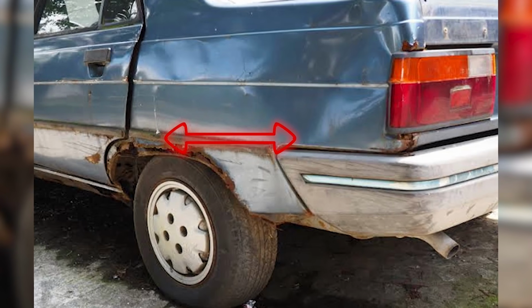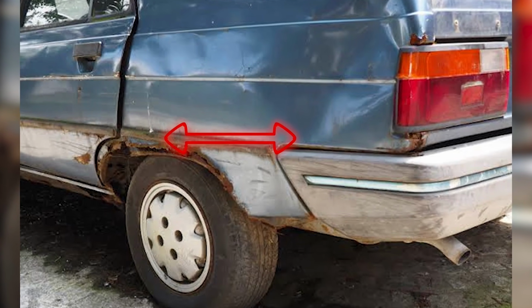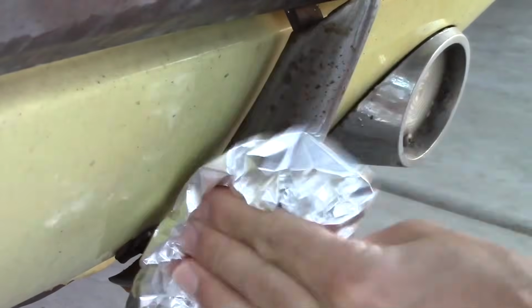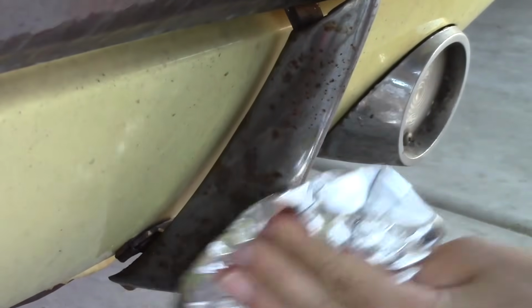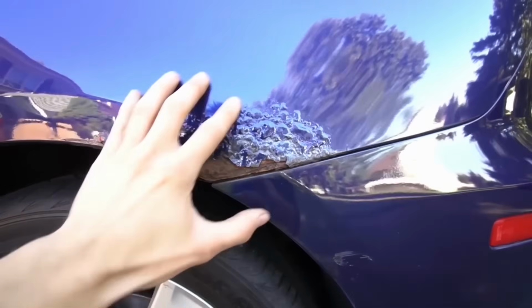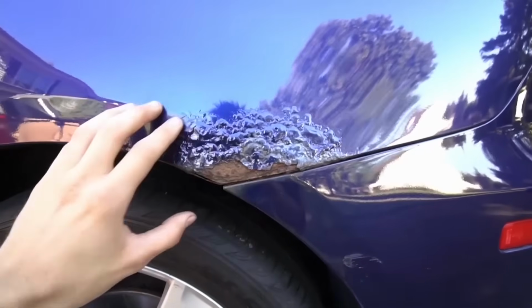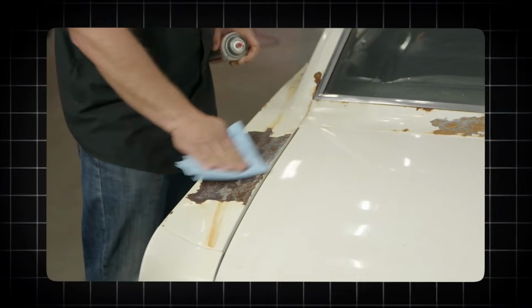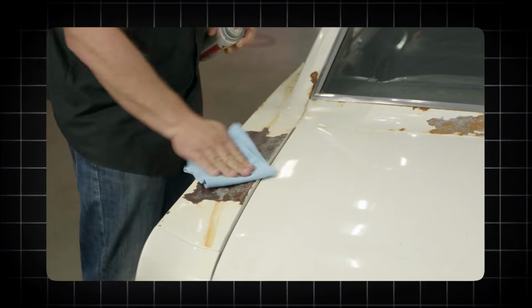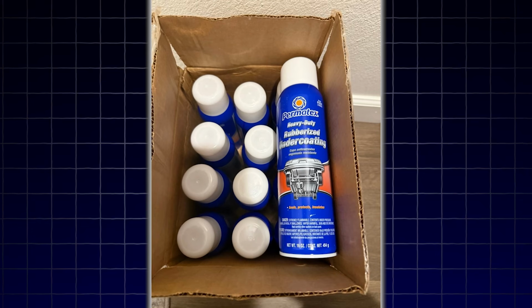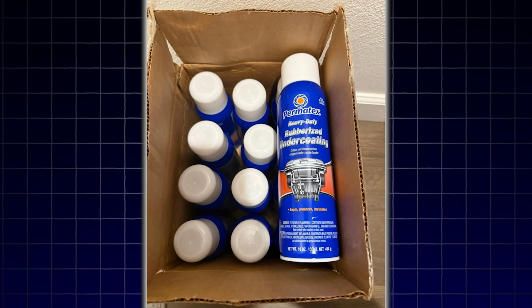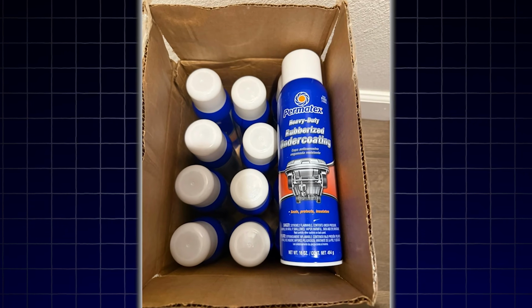The failure rate was significantly lower than all previously tested products. At the end of one full winter, approximately 8% of the treated surface showed edge penetration, compared to the 30% failure rate of the Rust-Oleum formula. 8% failure is meaningfully better than 30% failure, but it is not good enough for a product being relied upon to protect a frame through decades of northern winters.